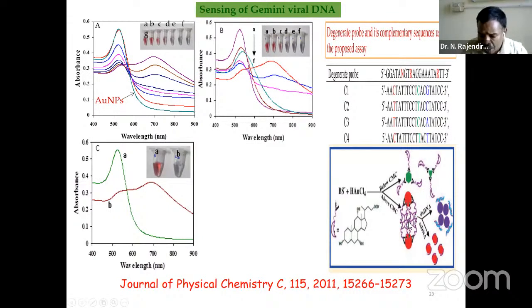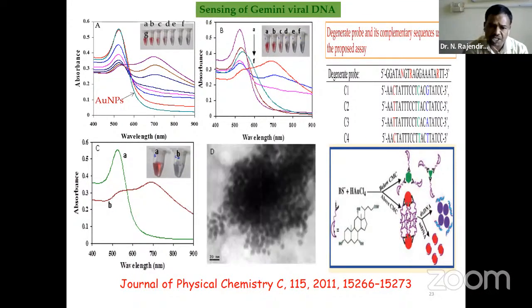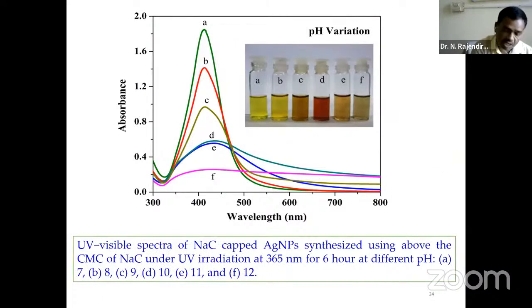Here you see the picture schematically represented after the addition of the single stranded DNA. This single stranded DNA covers the surface of the nanoparticles. It won't allow aggregation. However, after the addition of the complementary sequence, forming double stranded DNA, the single stranded DNA is removed from the surface, and the solution undergoes aggregation. So from this color change from red to blue, we can identify hybridization colorimetrically. Further, we confirmed this by transmission electron microscope. This paper was published in the Journal of Physical Chemistry in the year 2011.